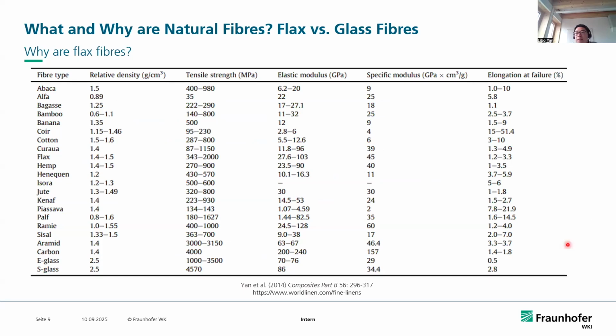Why flax? In this table, you can see I listed dozens of plant-based natural fibers. If we take a look at the tensile strength of the plant-based natural fibers, flax has the highest upper limit in tensile strength, up to 2000 megapascal, which is relatively close to that of the E-glass fiber.